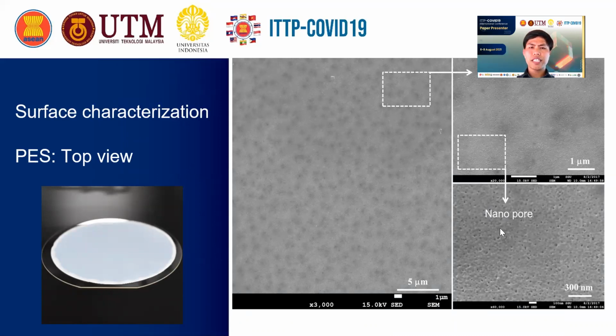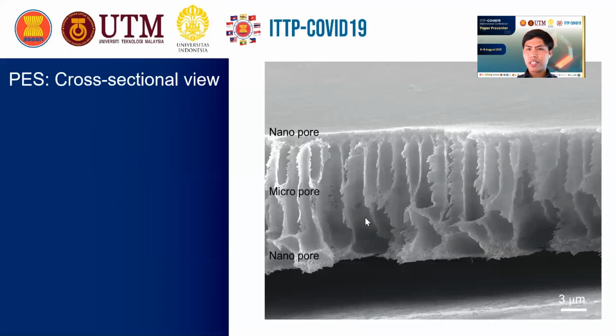Using the electron microscope, we see that there are nanopores on the surface of the PES. The nanoporous surface provides a smooth surface and also works as an absorption layer. Then, when we look at the cross-sectional view of our thin film polymer, we can see micropores in the matrix. The micropores can work as a pen to store the liquid from the ink, while the nano surface works as a filter that can separate the nanoparticles from the solvent. This is a pretty important characteristic of our printing substrate.